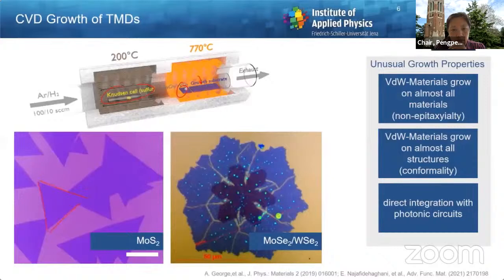And you can also change the composition of your precursors during the growth. And then you can, for example, also create heterostructures. In this case, we have a heterostructure of molybdenum selenide in the center, and on the outside it's tungsten selenide, and the transition edge between the two, the PN junction, if you so wish, is of epitaxial quality.